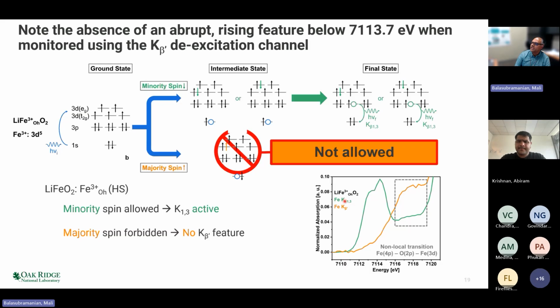However, when you monitor it with the iron K beta 1,3, because this transition is allowed, you would see an emission corresponding to the K beta 1,3. And so you will see this classic doublet structure that is expected for iron 3+ in an octahedral site. Additionally, there is this feature that you see, and it is known by prior studies in transition metal oxides that such features arise from non-local transitions. That is, from the iron 4p to 3d. You excite a 1s electron with a mixed non-local iron 3d of the neighboring iron atom. And we will not discuss this transition further, and we'll concentrate on this transition which are local to the iron atom.